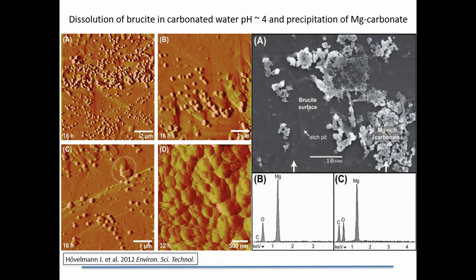And when we add the carbonated water, all I did was to bubble CO2 into pure water. Within a few minutes, the pH had gone down to about 4. I pass that over the surface because, of course, I'm working in a fluid cell in the AFM. We get nanoparticles, and you can see the triangular edges of the original etch pits are now covered with nanoparticles, which merge together to form a larger form, and very often at the ends of the etch pits,